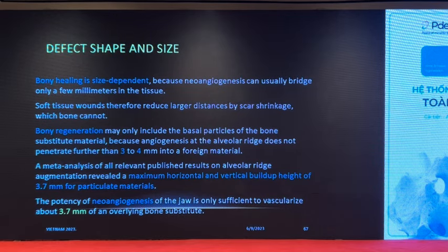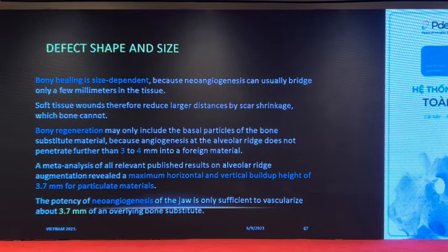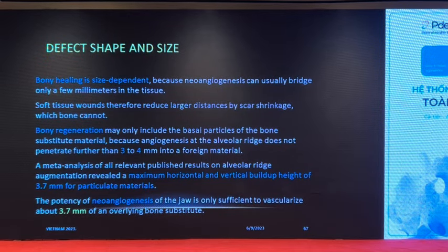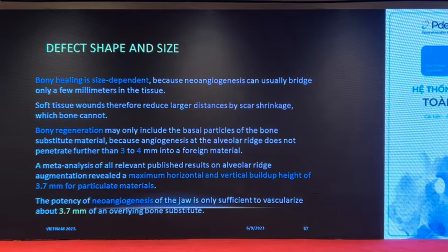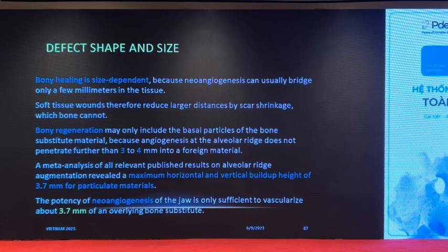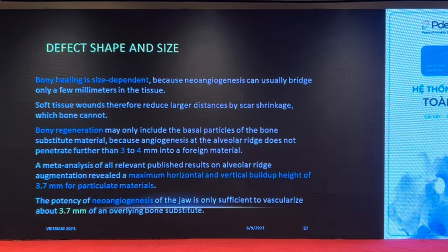Angiogenesis at the alveolar ridge does not penetrate further than 3 to 4 millimeters into foreign material. A meta-analysis of all relevant published results on alveolar ridge augmentation revealed a maximum horizontal and vertical buildup height of 3.7 millimeters for particulate materials.